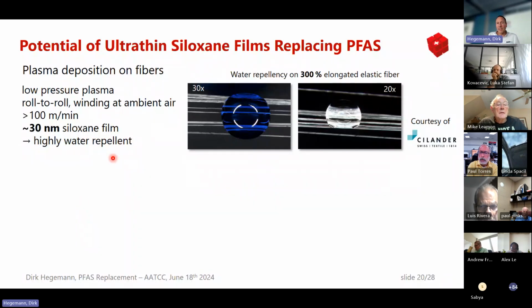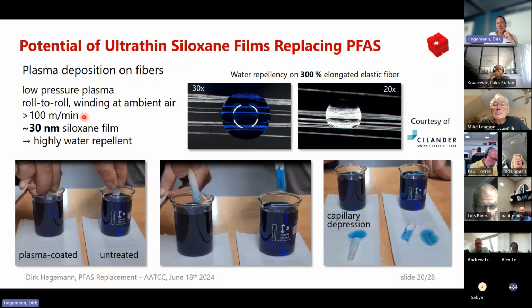We do this directly on the fiber, on yarn material, because this way we get the best, let's say, treatment on every filament. So we wrap every filament with a very thin siloxane film. We do this at high speed. It can also be transferred to industry. That is the next step we are doing.